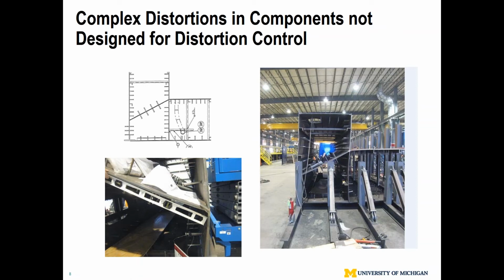So this is from Marshall Space Flight Center as a part of the Orion rocket program. There's a simulated component. Obviously, I cannot show anything related to an actual component, so this is a test article. Before friction stir welding of two rings, in this view you cannot see it, but each half is about 6-7 inches wide and about 6 millimeters thick. Before welding, the circularity and everything looks good. After friction stir welding, you can see the friction stir weld.